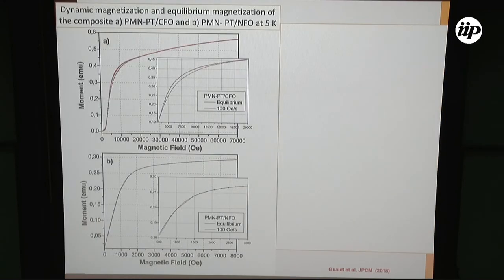To check this idea, I performed magnetization as a function of applied magnetic field at different rates of the field. The black curve is the equilibrium one: the magnetic field is applied, stopped for 10 seconds, and the magnetization measured. In the other case, I performed a sweep at 100 Oersted per second on the sample. A clear difference is observed in the PMN-PT cobalt ferrite curve, while the nickel ferrite at 100 Oersted per second and in equilibrium condition gives the same magnetization as a function of the field.